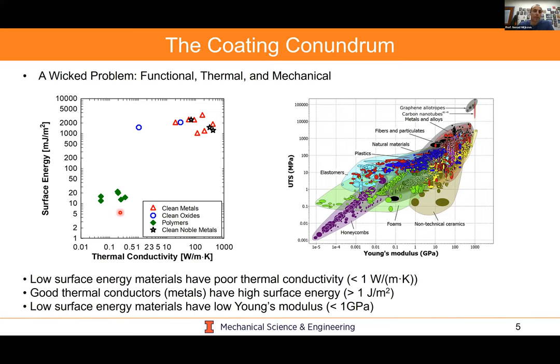Now, at the same time, if you look at the ultimate tensile strength of common materials and plotted as a function of Young's modulus, you could see that these fantastic materials for coating applications, which are up here, looking at carbides, graphene allotropes, common materials, metals, that actually have very high strength, they actually are also very high surface energy. At the same time, if we look at natural plastics, elastomers, which are common materials for hydrophobicity, they both tend to have small ultimate tensile strength and small Young's modulus. And so I have it down in these three bullets down here that what we'd like is low surface energy, which we know have poor thermal conductivity. Good thermal conductors, such as metals, have high surface energy, and low surface energy materials have low Young's modulus, which is really what drives the research we do in lab, is to try to develop coatings which can overcome these challenges and mix and match these advantages of the different materials that we develop.